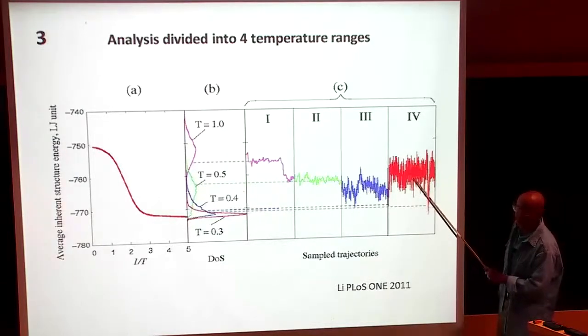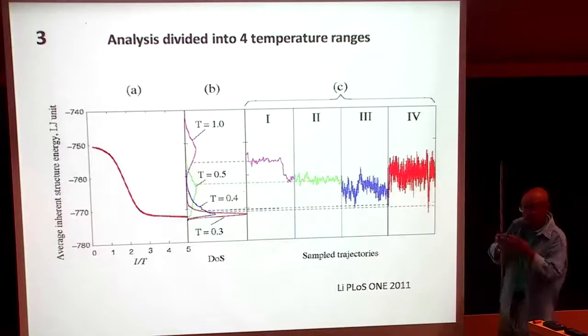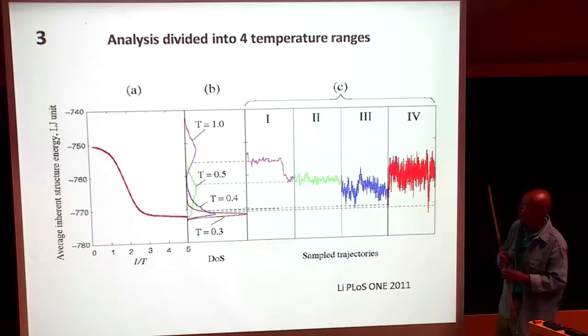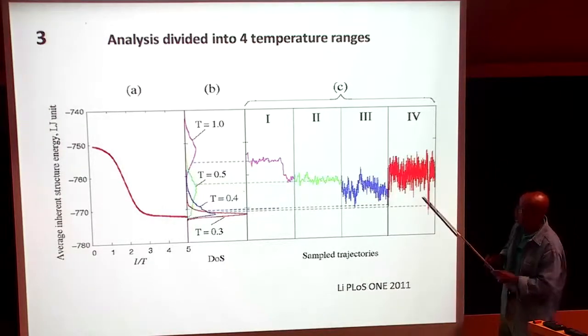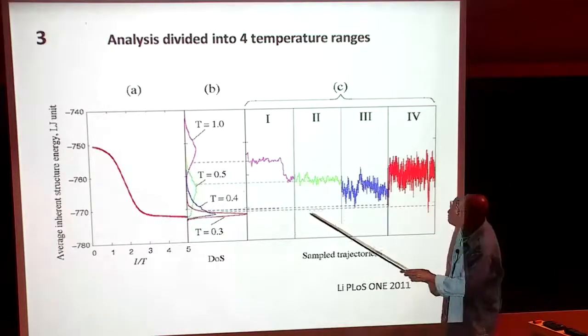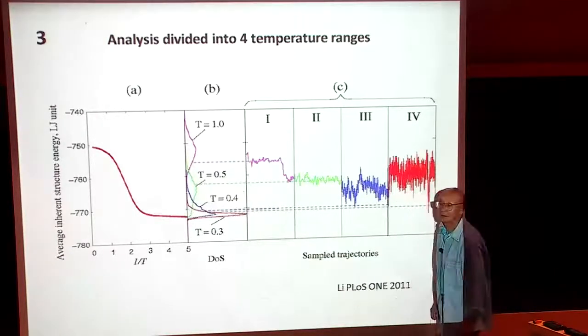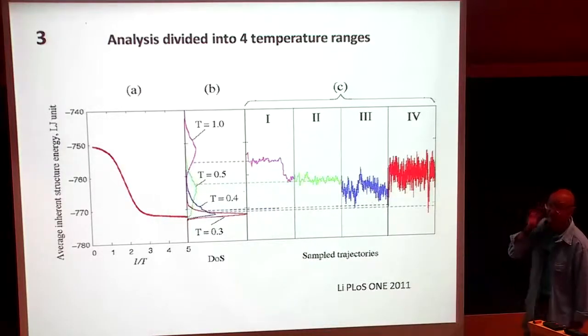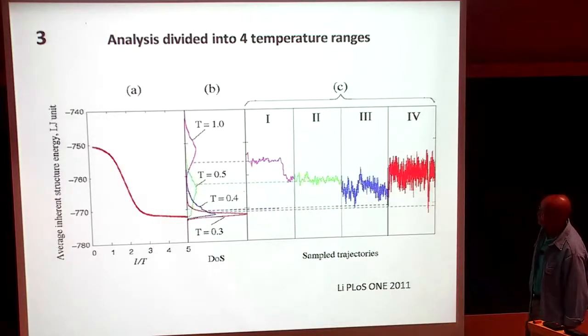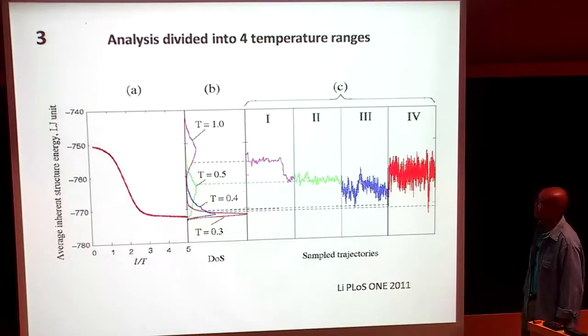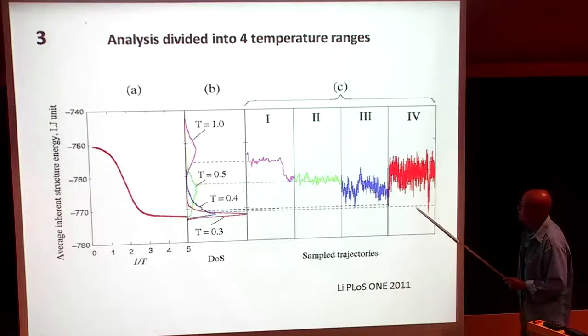Yeah, well, you're right. It turns out that Stillinger talks about these energy landscapes in terms of broad basins. You're right, in this sampling we have only seen about 2 broad basins. So the initial point of panel 4 was picked from one of the points distributed according to panel B. Look at each of these horizontal dashed lines: the first 2 of them sort of go through where the activation is, the third, the blue one, is a bit off, and the red one is way off.